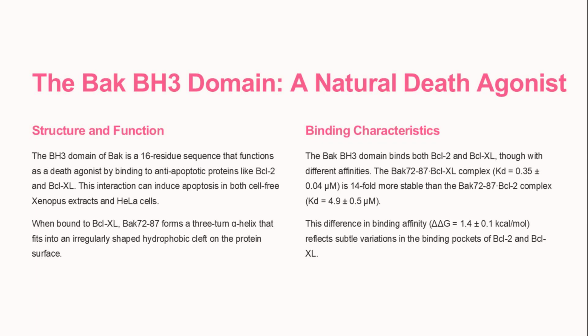When the BAK BH3 domain binds to BCLXL, it forms a 3-turn alpha helix that fits into a hydrophobic cleft on the surface of BCLXL. The BAK BH3 domain binds to BCLXL with higher affinity, Kd equals 0.35 μM, compared to its binding to BCL2, Kd equals 4.9 μM. This difference in binding affinity is about 1.4 kilocalories per mole, reflecting subtle variations in the binding pockets of these two anti-apoptotic proteins.